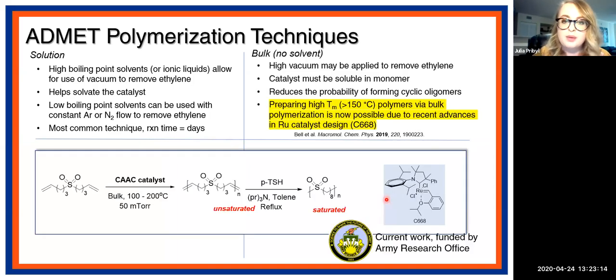The second most common approach is a bulk technique. So this means that you simply have the catalyst and your monomer and absolutely no solvent. So this is nice because then you can apply high vacuum to remove the ethylene to drive the reaction forward. The catalyst must be soluble in the monomer to use this technique. And also this technique reduces the probability of forming cyclic oligomers because when you have only bulk monomer around, the chain end is more likely to see a monomer unit rather than to see the other end of the polymer chain, which is nice. And recently we've been using this technique to prepare high melting point polymers.